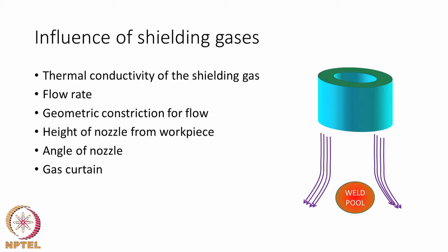So, we must understand that the shielding gas that is being used to protect the weld pool also has thermal conductivity, which means that it also can remove the heat, and therefore, we also have to pay attention to what the shielding gas is that we are using. If it is, for example, argon versus helium, then we know that helium has higher thermal conductivity, which means that the heat loss is going to be more if helium is used as a shielding gas, and that information should be reflected in the heat source formulation by a change in the efficiency or a change in the nature of the distribution.